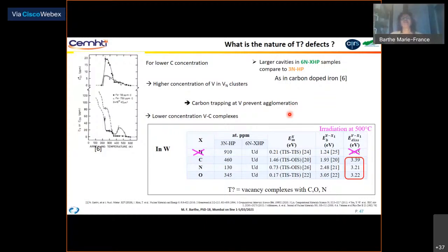So we think that we observe the same kind of phenomenon in tungsten. If we come back to the properties of the different light elements in tungsten, and we calculate the dissociation energy for this complex VX, we can see that at 500 degrees C, the hydrogen cannot be considered because this dissociation energy is too low. But all these complexes with carbon, nitrogen, oxygen could still exist at 500 degrees C.